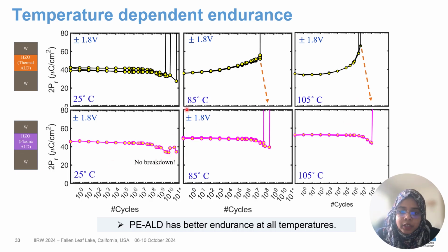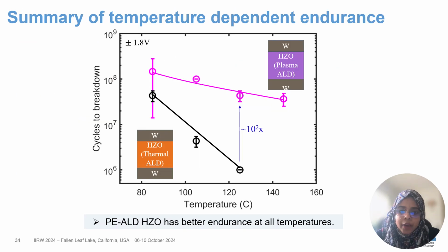And this difference in endurance is more prominent at 85 and 105 degrees Celsius. What we are seeing is that the thermal ALD device is breaking faster compared to the plasma ALD device in both the temperatures. And we have measured multiple devices in each case here. So next we have tried to summarize the endurance data that I was showing in the previous slide. Here you can see that the x-axis is temperature and the y-axis is cycles to breakdown, or endurance.